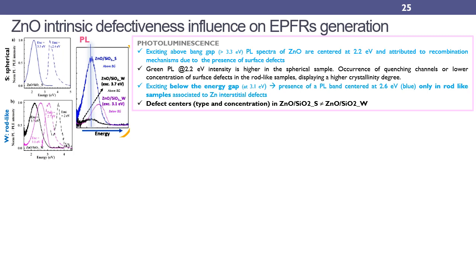Moreover, zinc oxide on rod-like surface can be excited with energy below the band gap at 3.1 electron volt, and the following emission is peaked in the blue range at 2.6 electron volt. Silica support signal under UV is negligible. These results indicate that morphological factors in terms of size, growth parameters, and interfaces are strongly influencing the type and the concentration of surface defects of the zinc oxide nanoparticle, and as a consequence, their optical properties.